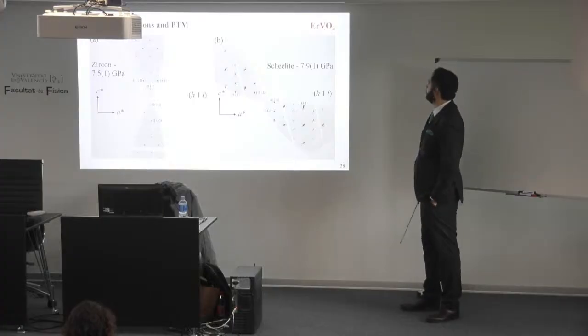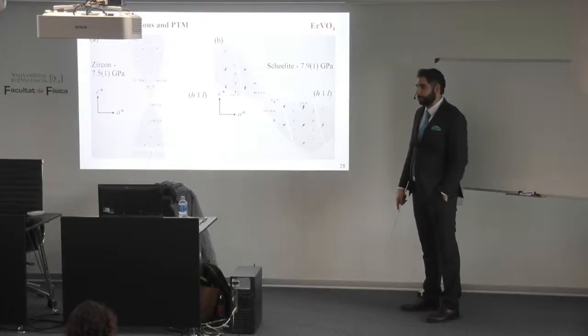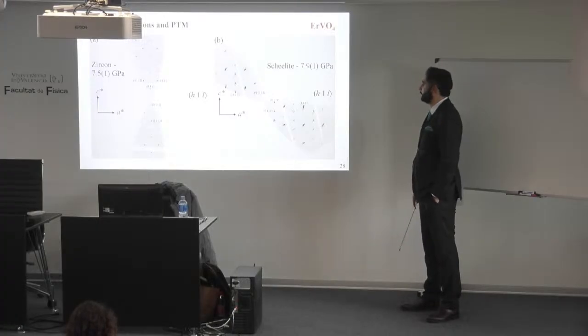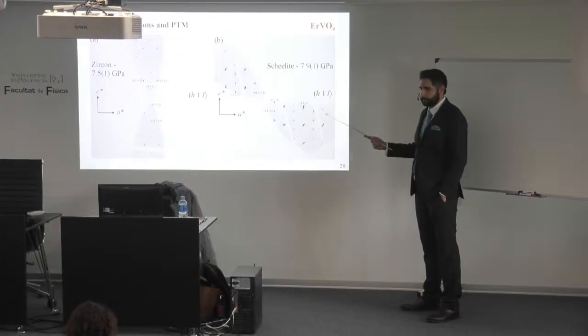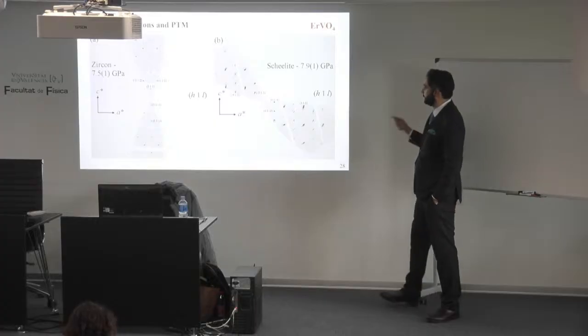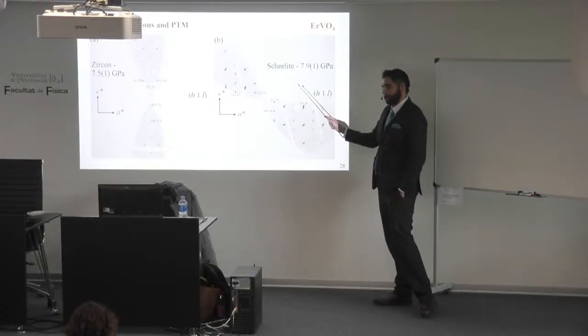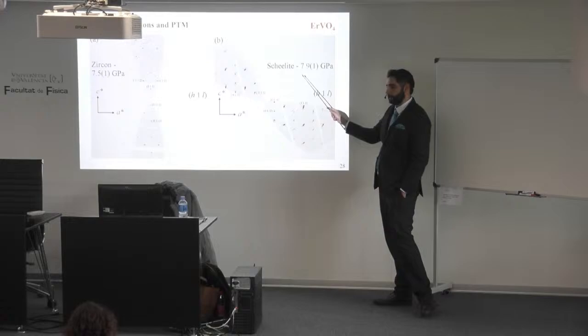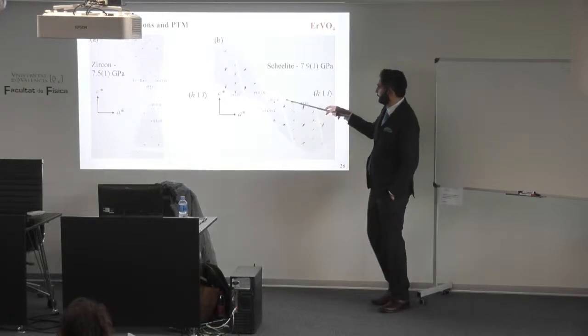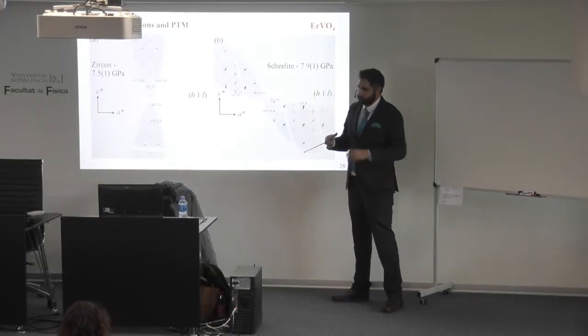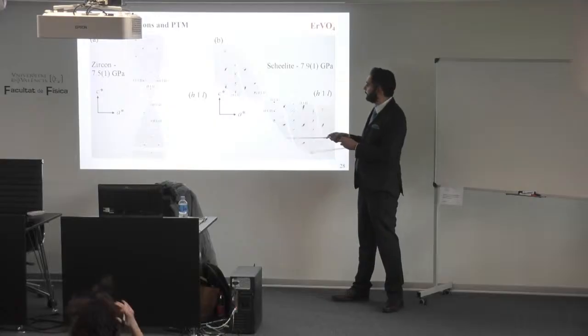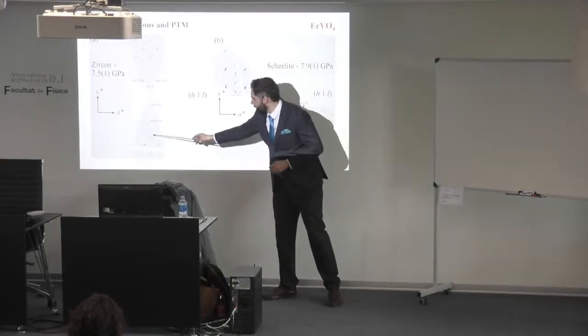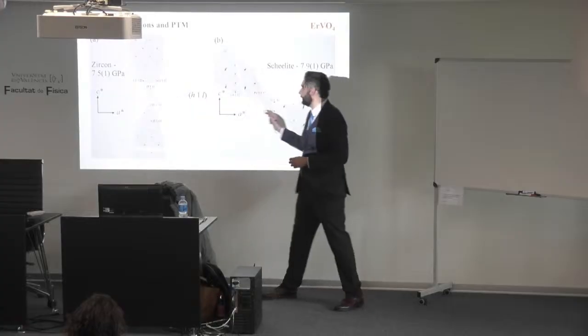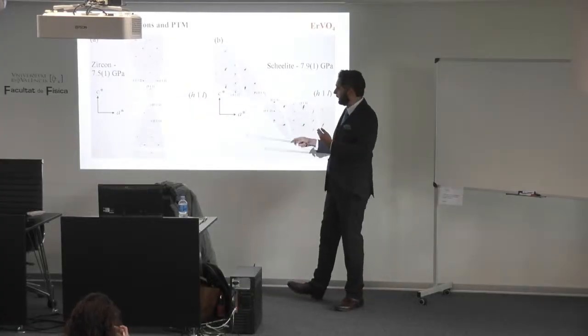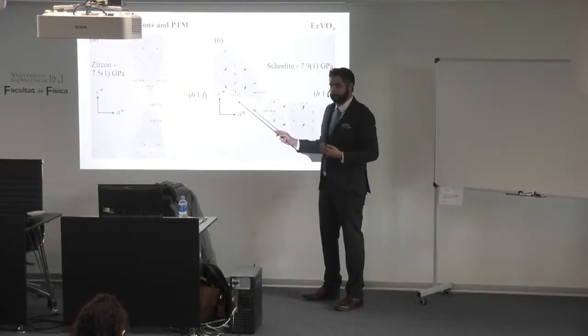Okay, for erbium orthovanadate, the lucky one, we confirm that this phase transition has no structure in between, and we saw single crystal behavior of the scheelite state. In this case, we see that the dots are a bit distorted and bigger, but this square-like signal of the same cut in the reciprocal space have different shaping.